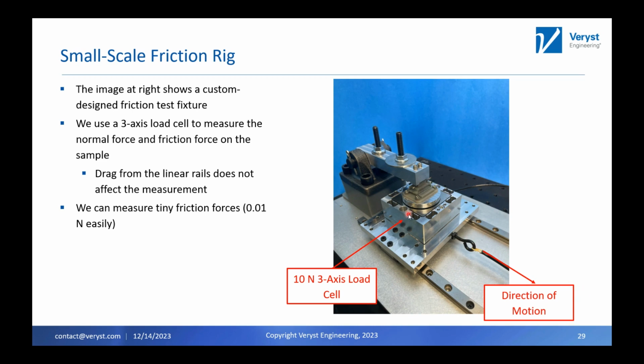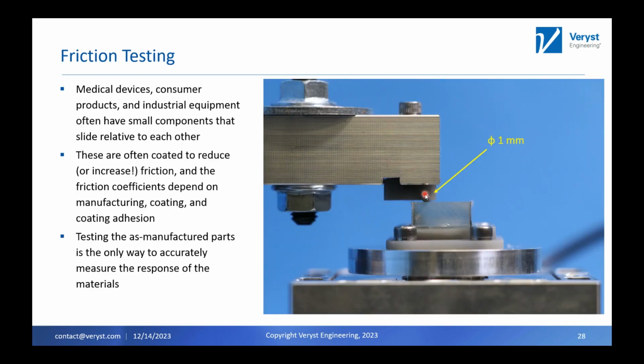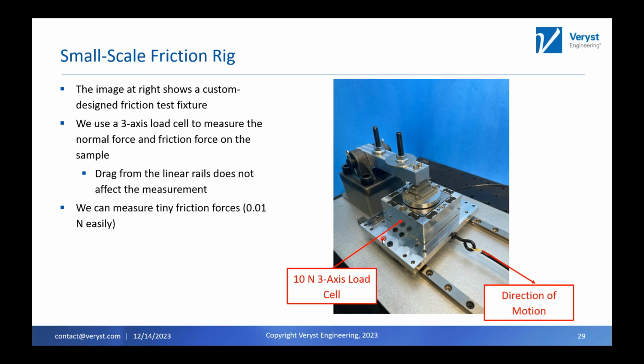So in my opinion, the beauty of this design is that we're measuring the normal force and the friction force throughout the entire test before we get any of this motion. Right? We're measuring the friction, if I go back a slide, between this surface, and this right here is our load cell. There's nothing in between to add any drag from those linear bearings. We don't care how good those linear bearings are. They just need to keep us on track and make sure we're going in one direction and keeping things perpendicular. So as I said, it's a 3-axis load cell that's 10 newtons.